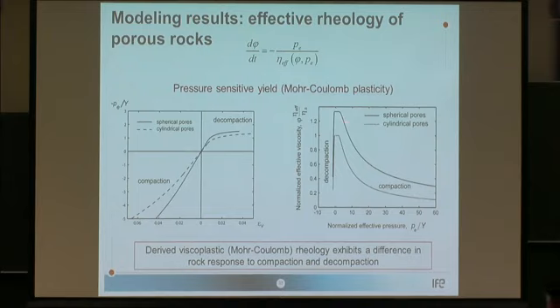Here is an example with Mohr-Coulomb plasticity, when our yield criterion is better described by Mohr-Coulomb plasticity. And this happens at much lower effective pressures. So what we see, this is again a pressure-strain curve, is that our stress-strain curve exhibits a difference in behavior between decompaction and compaction. This is what Connolly and Podladchikov call decompaction weakening. So we do have a difference in rock response to compaction and decompaction, and here is effective viscosity again as a function of pressure. During decompaction, our viscosity drops very significantly, while for compaction, yes, it drops, but much slower. And this rheological asymmetry was quite a big deal, around which Connolly and Podladchikov developed their porosity waves with elongated channels.